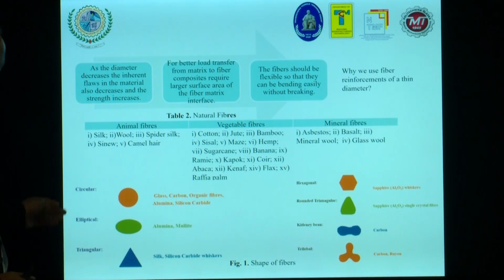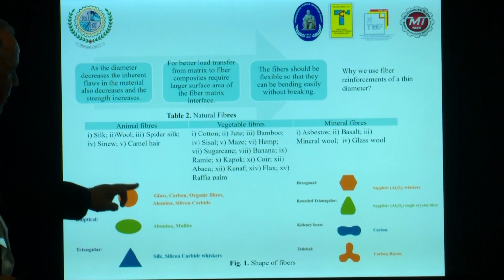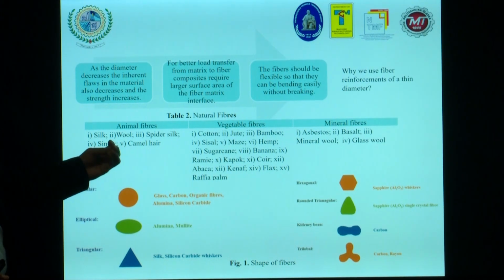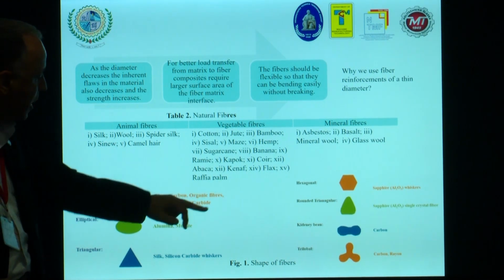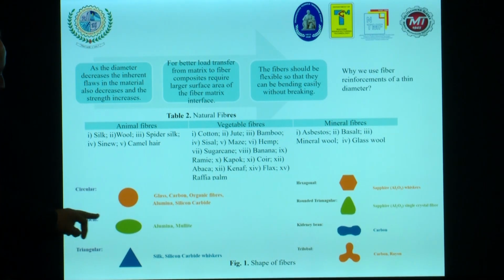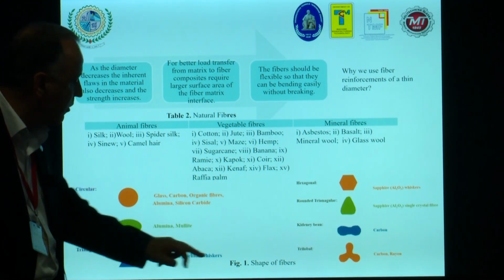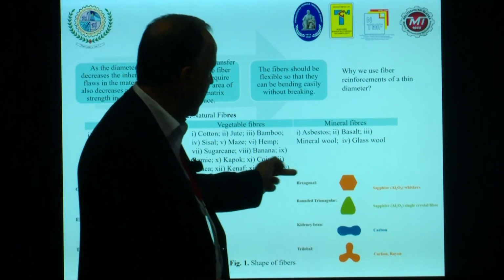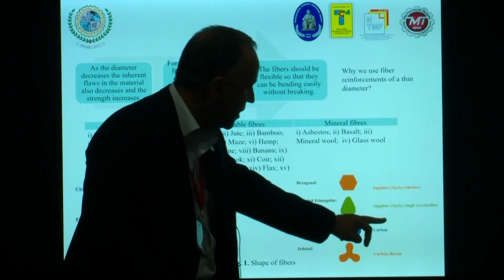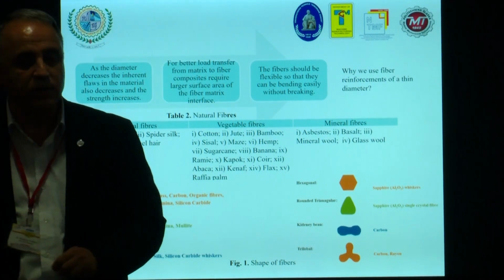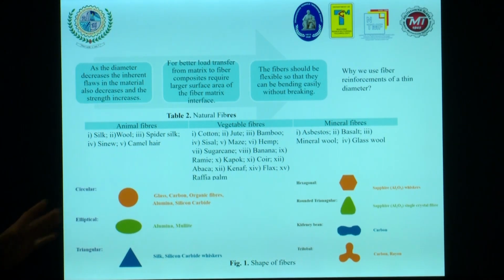I put also here some shapes of the fibers, I mean circular one, and you can put the names glass, carbon, organic fibers, alumina, silicon carbide, elliptical shape, alumina, mullite, triangular shape, silicon carbide whiskers, and of course another, you can see hexagonal one, rounded triangular one, kidney bean in case of carbon, and trilobal shape in case of carbon and boron. So these are the main shapes that we can use inside of composite material as reinforcement.